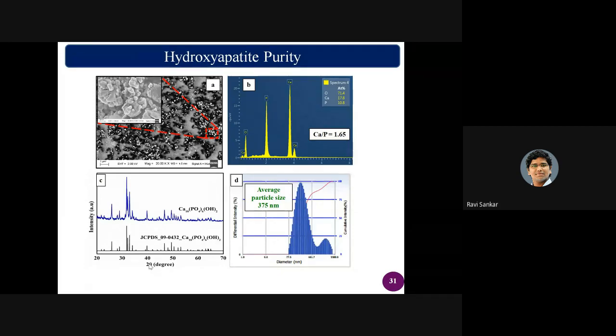the peak intensity method, from which you can guess qualitatively what the purity of the material is, whether it is 99% pure or 90% pure or 60% pure or something. Since it is a biomaterial, you should always try to make it 99.2 or 99.5 and above. In that circumstance, what we have done is that you can also go for another analysis that is called Rietveld analysis. So these two methods will give you the purity of your material.